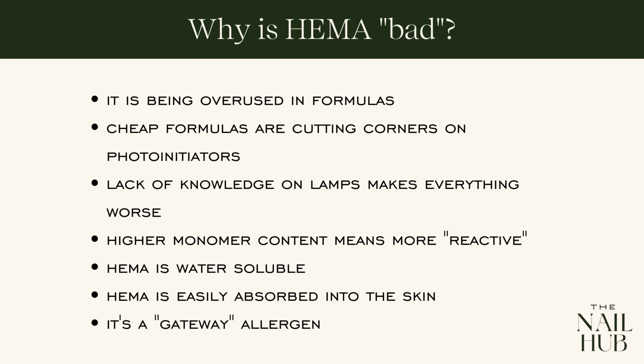Lack of knowledge on the importance of nail lamps also makes the HEMA conversation 10 bazillion times worse. If our product isn't fully polymerized, and this also goes into liquid and powder as well, if we don't have that right ratio between liquid and powder, we can end up with a very soupy mess or a very dry bead that doesn't fully polymerize on the nail, and that can leave unpolymerized product inside of that acrylic.